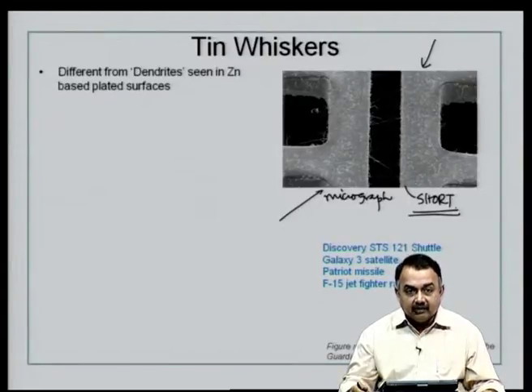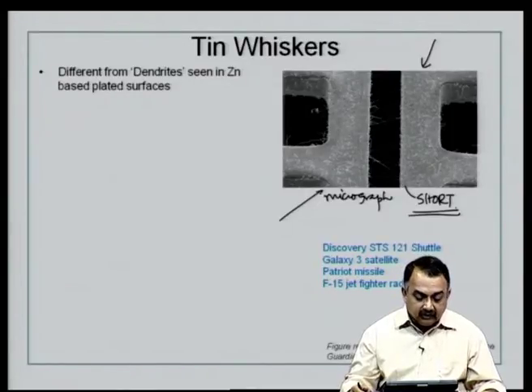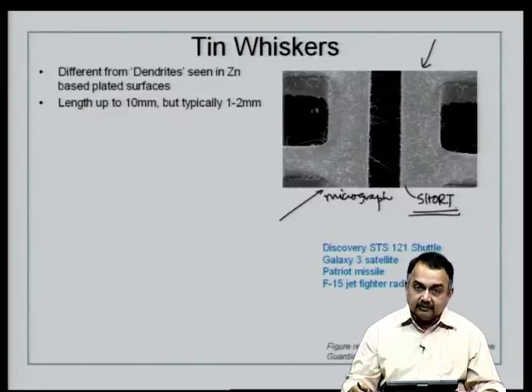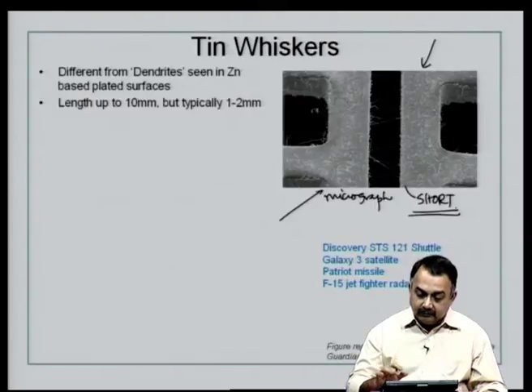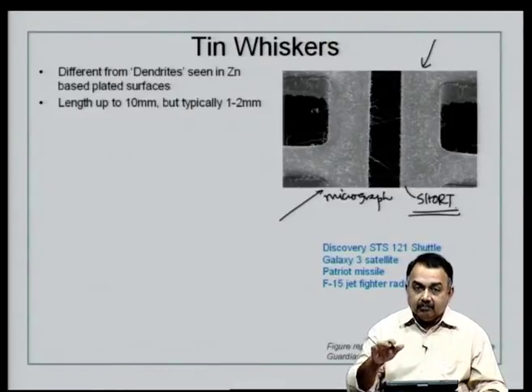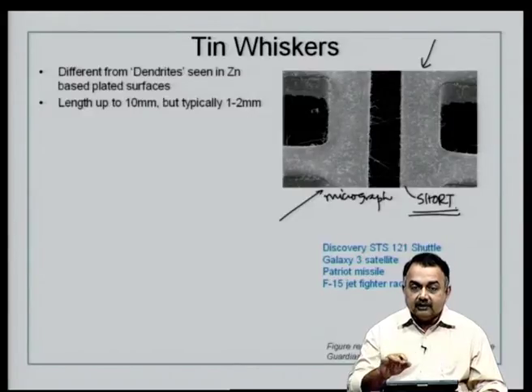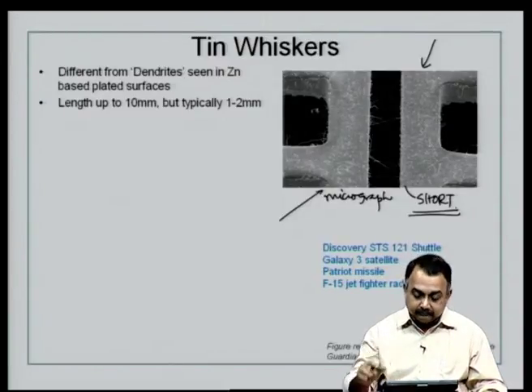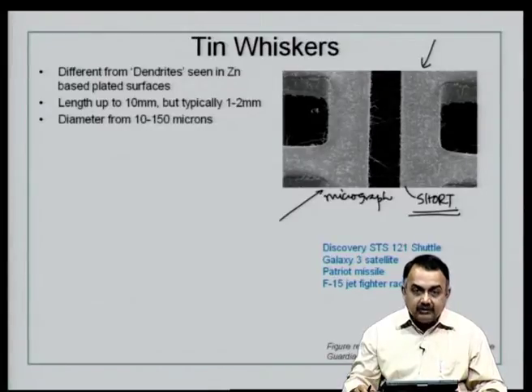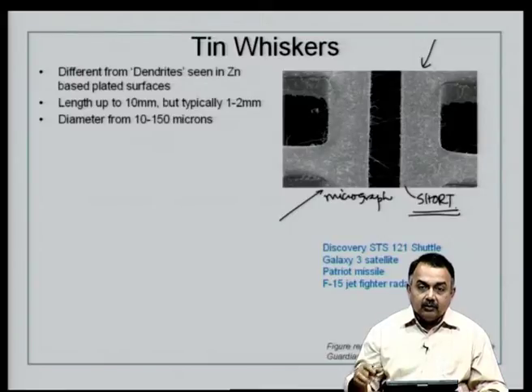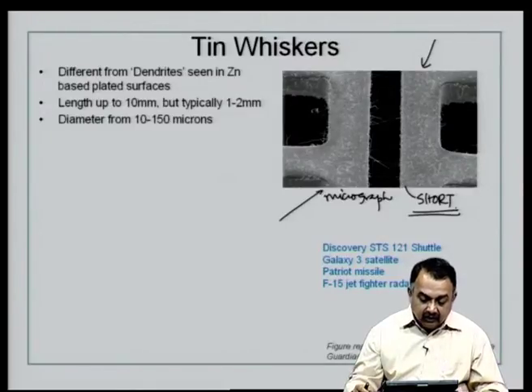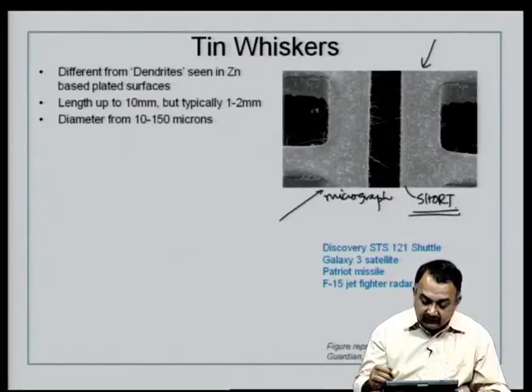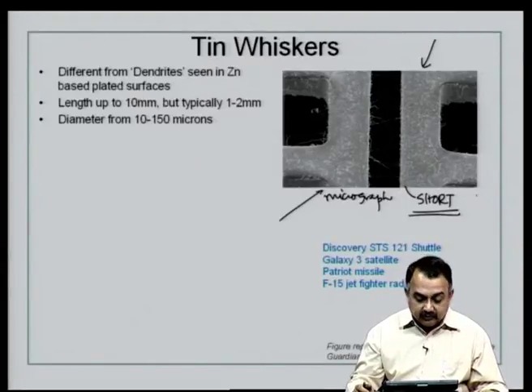They are different from dendrites. If you are aware of this term dendrites, which you normally see in zinc plated surfaces, tin whiskers are normally seen in tin plated surfaces. So, here in PCB, this phenomenon that you are seeing in this micrograph is an example of copper plated with tin. There is no other intermediate interface, and the components have been soldered on tin surface, which means you are providing more tin over time, and these whiskers are formed due to various factors, which I will explain shortly.